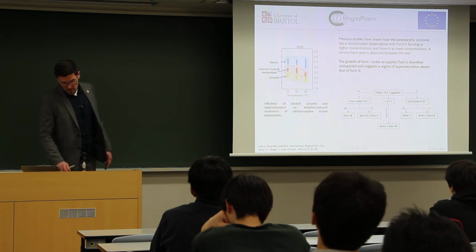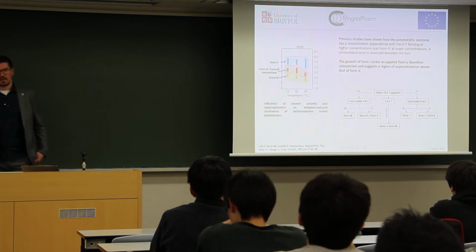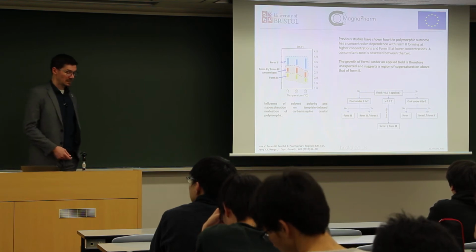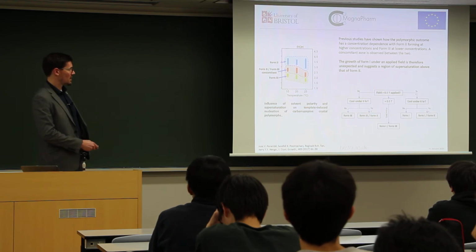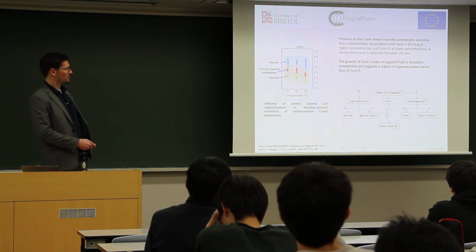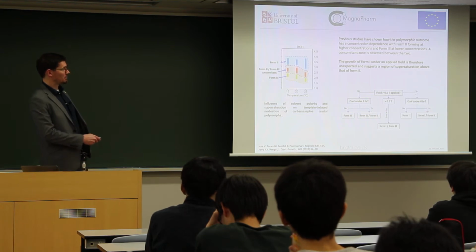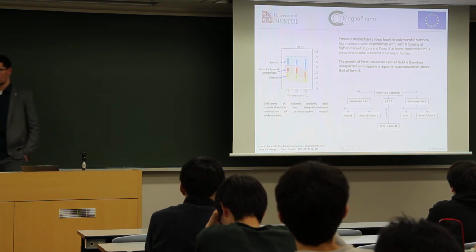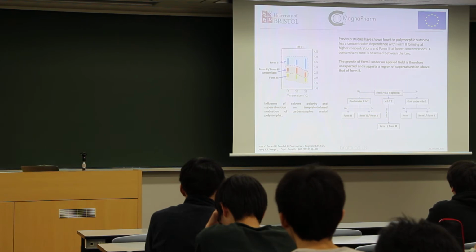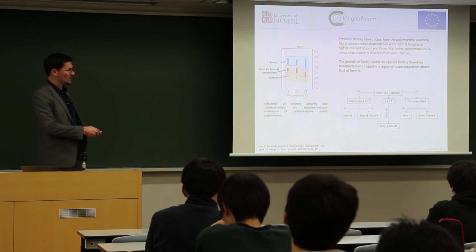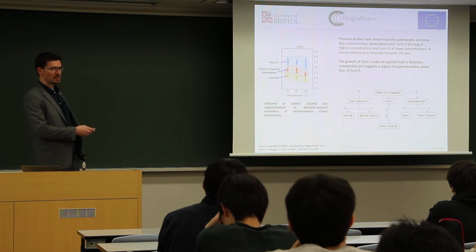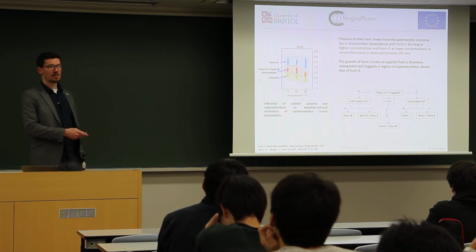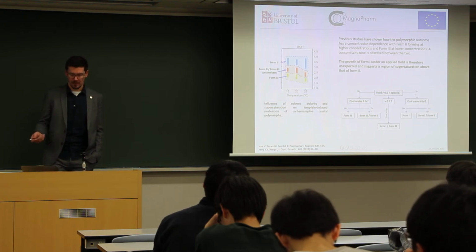However, as I said, it was a very well-studied material, and what we know about this is from a paper published by Parambil, 2017, I think, who basically did a concentration study with carbamazepine and said the more saturated your carbamazepine solution, the different forms you get. So you get form 3 at low concentrations, form 2 and form 3 concomitantly as you increase the saturation, and form 2 at the top. We were getting form 1.